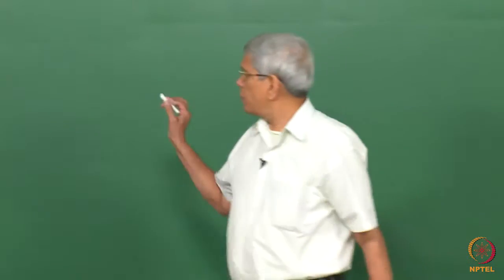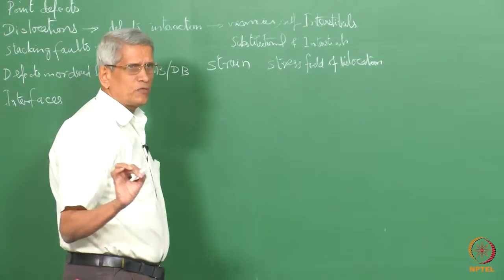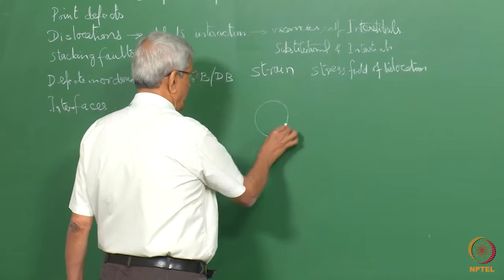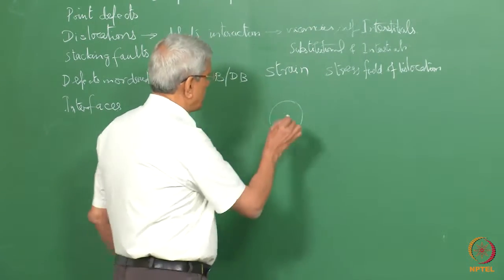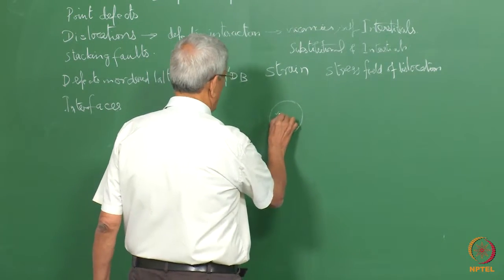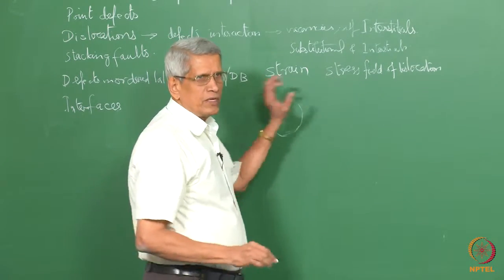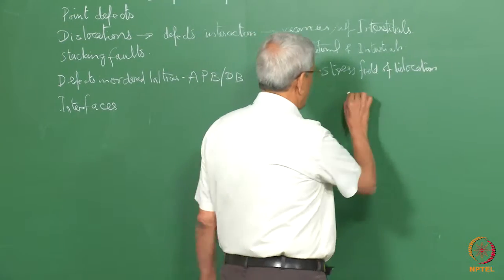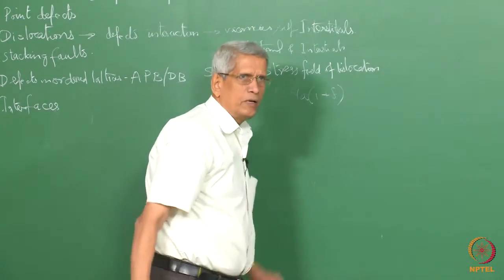Suppose we assume, in the simplest way, that a vacancy or a defect is there. Assume some area of the sample into which we are putting a defect. Maybe the radius of it is R_A. Into this region we are introducing a defect which has a radius R_A times (1 plus delta), where delta is the misfit parameter.